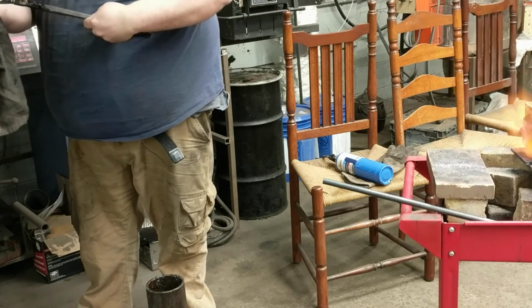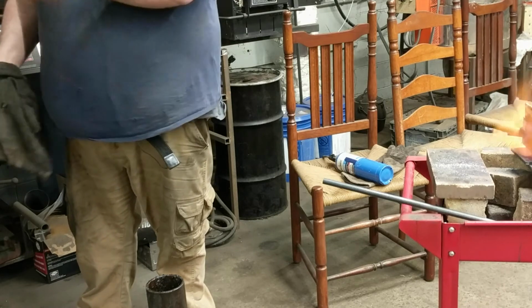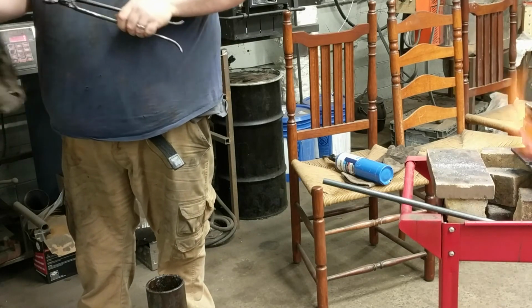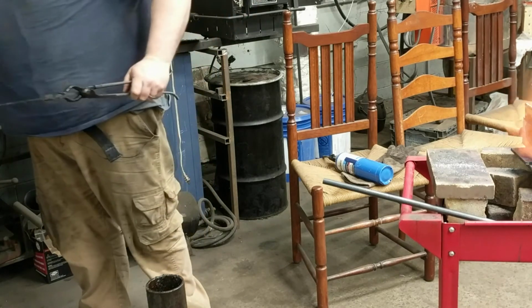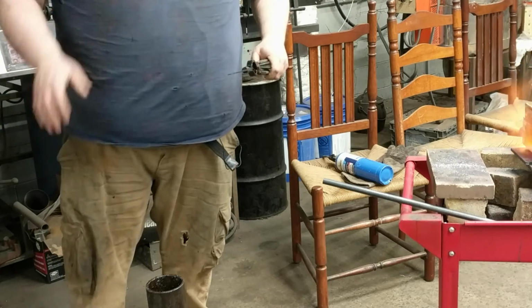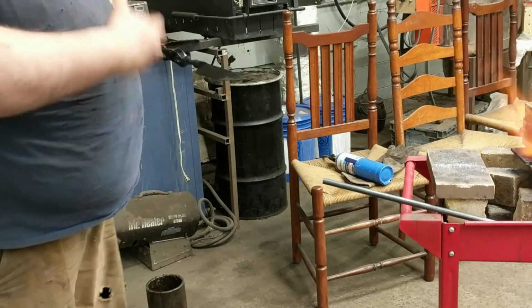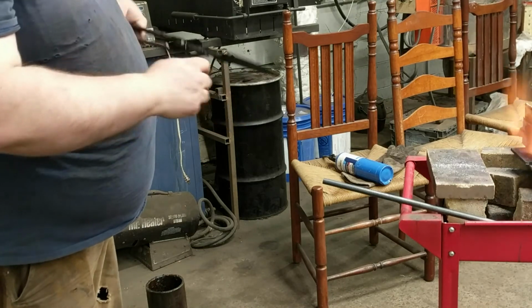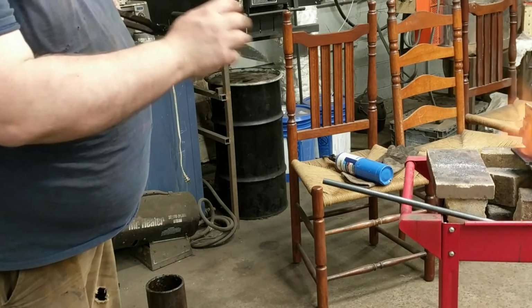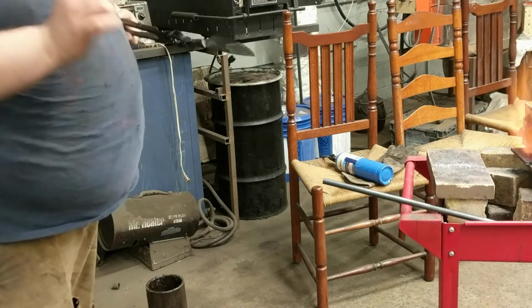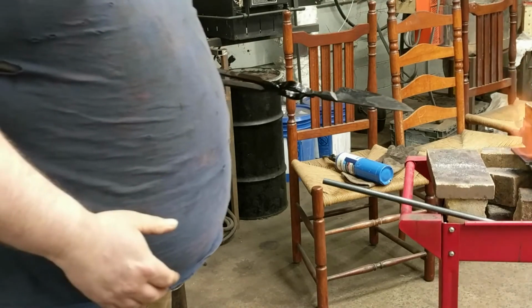Where are my arms? There we go. Cool. Now, because I went several cycles, I won't get this everywhere, but I built up a little bit of scale. When you see this white like this, where it pops all the scale off, it's a really good indication that you went the proper temperature and you quenched fast enough. Shut this off.